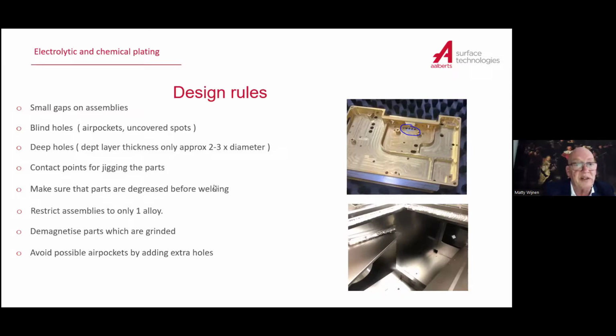Make sure the parts are degreased before welding, because welding is mostly done on parts which are just manufactured and have oil. And if you weld them, you can get oil in the weld itself, and that will come out due to the plating or the etching, and can also create bad adhesion. Restrict assemblies to one alloy, because every metal has its own pretreatment. If you use different alloys, different metals, you have a problem.